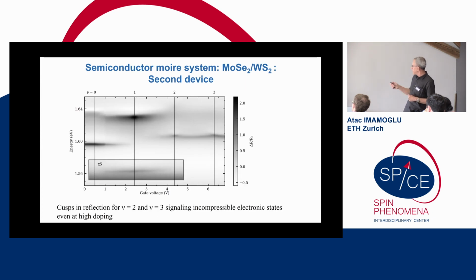This is another device, and these gaps at nu equals 2 and 3 are generic signatures of incompressibility in the system. We only see signatures of incompressibility at integer fillings, but other materials show also fractional fillings, and most likely if we had more sensitive probes, like a sensing layer like they do at Cornell, this would also be seen.